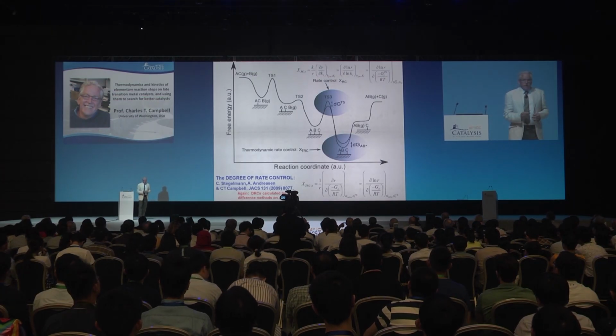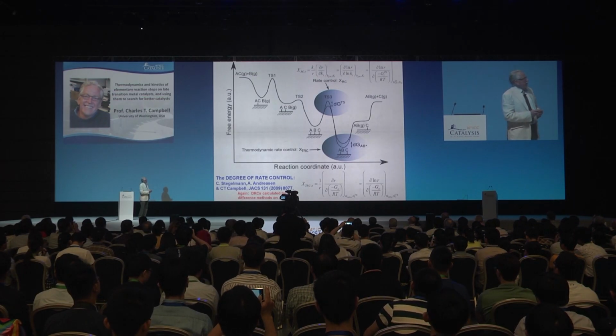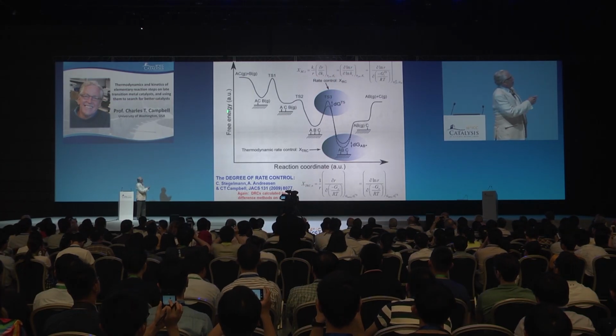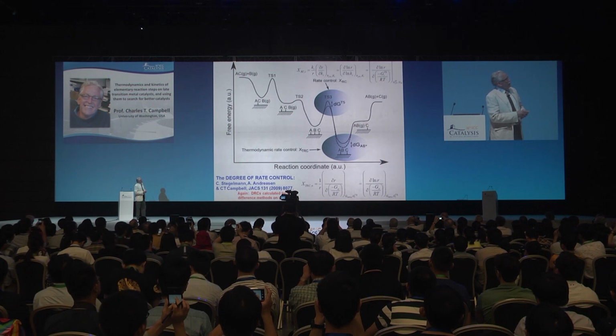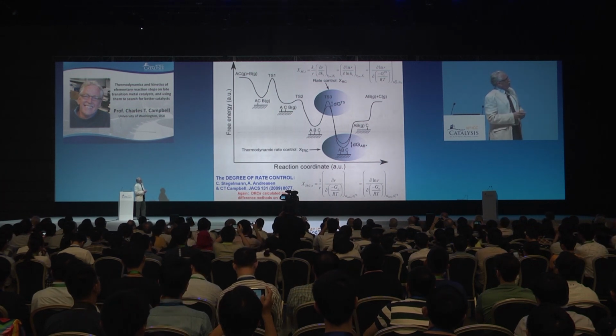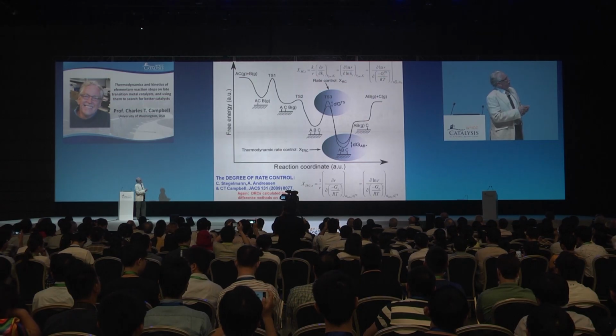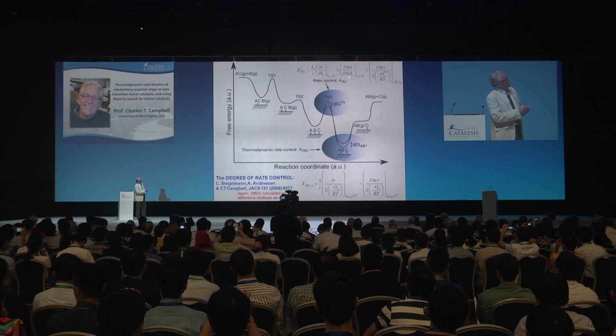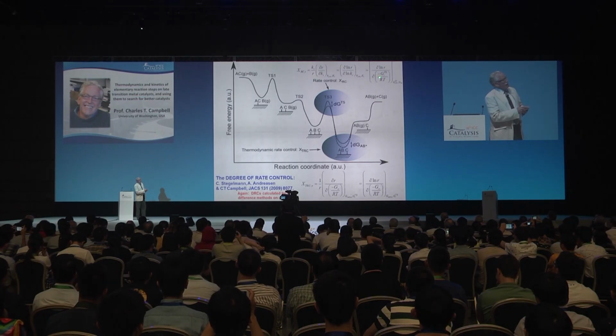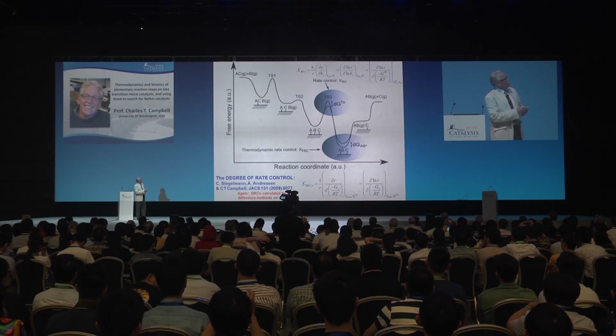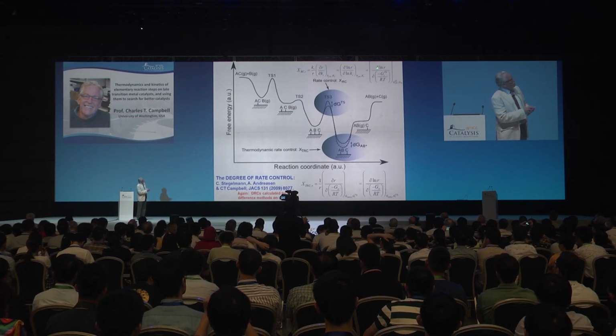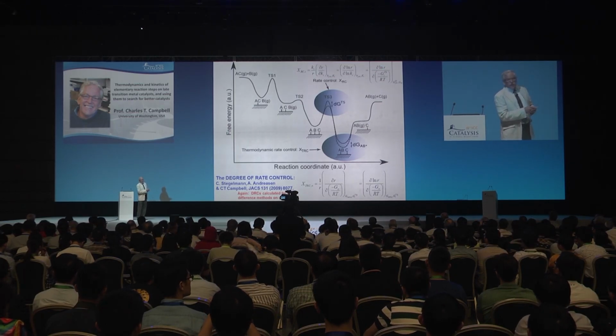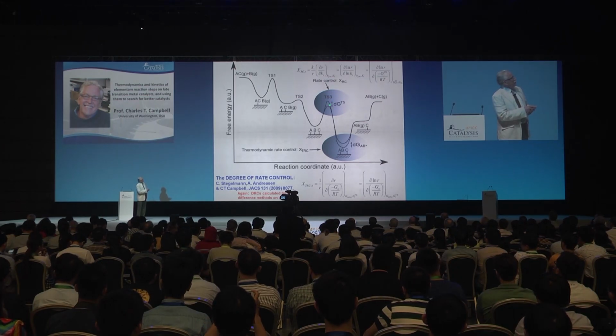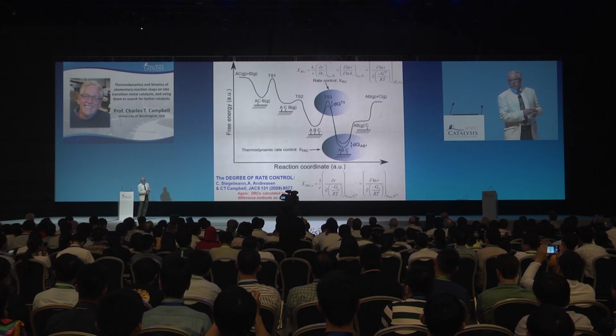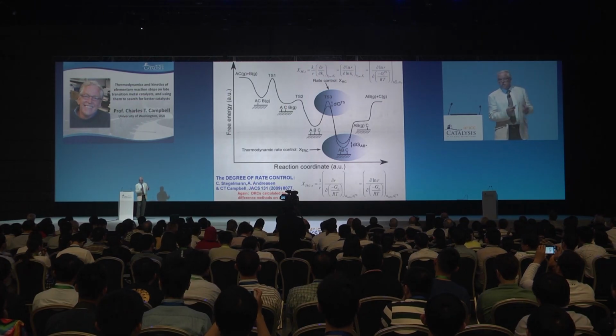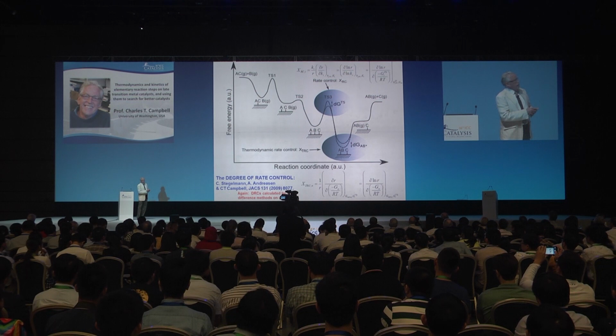And it's best to picture the meaning of that concept when you look at it on a standard state free energy diagram for the overall reaction, where there are many elementary steps. And so this degree of rate control, if you expand the rate constant in terms of the standard state Gibbs free energy of the transition state for that elementary step, it really tells you what's the fractional increase in the reaction rate per unit stabilization of the transition state for that elementary step. And that number is 1 for the rate determining step.